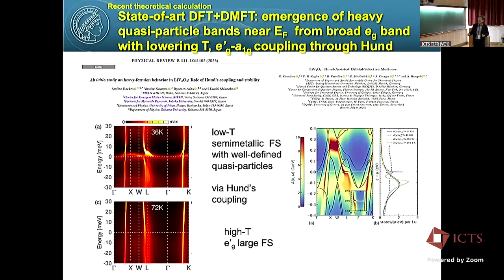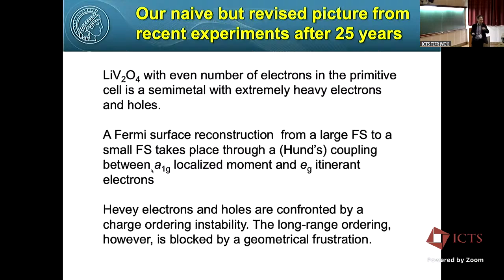On top of that, Arita changed the temperature from low temperature, 30K, to 70K. And those heavy quasi-particle bands, electron and hole, disappeared. And you see only the big Fermi surface coming from E prime G. So there is a coupling-decoupling crossover between these two temperatures. Okay, so that's fully consistent with the interpretation. So this is my answer sheet.